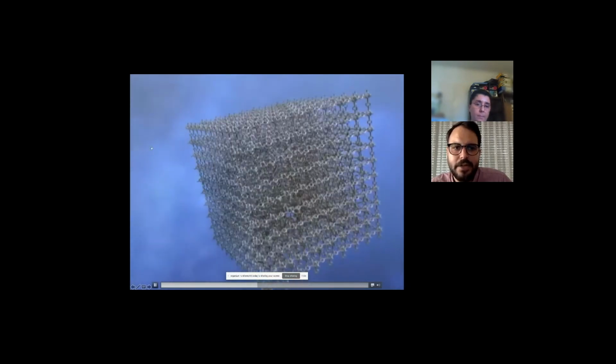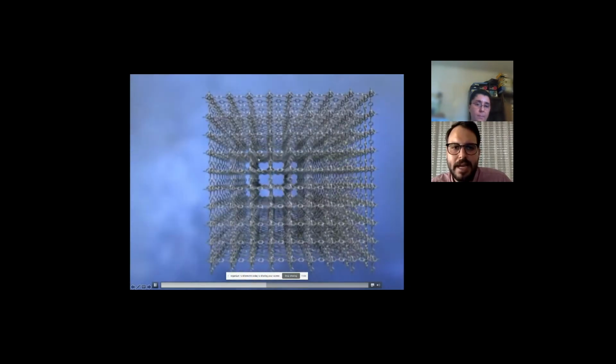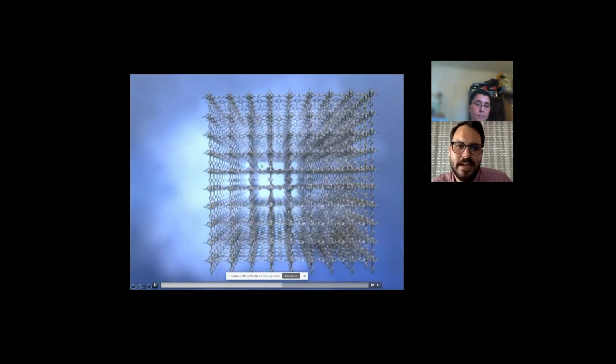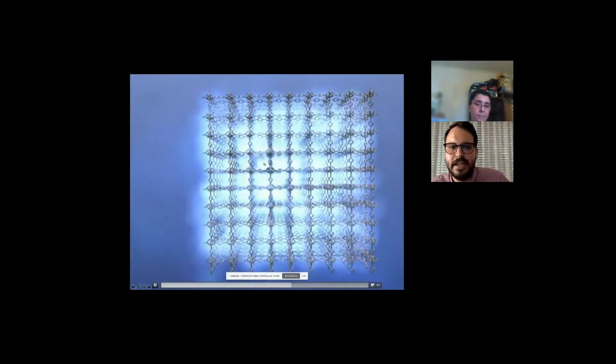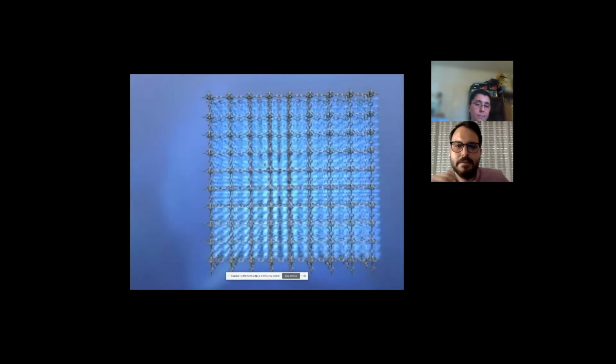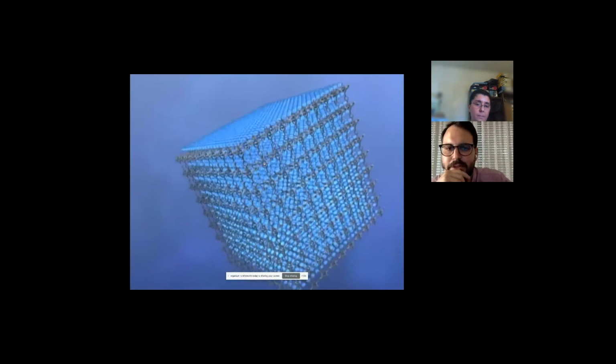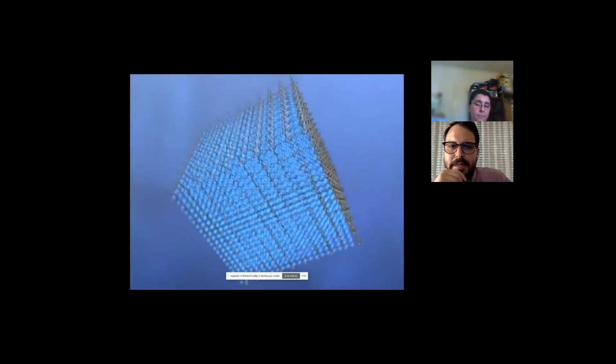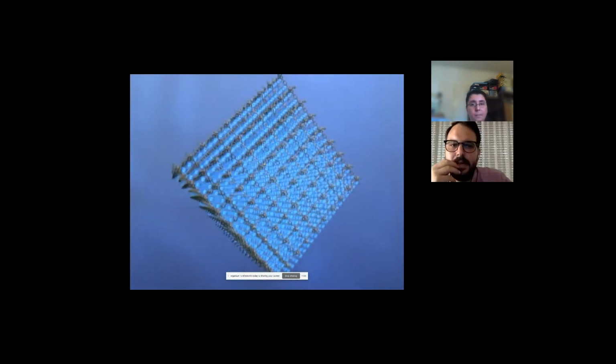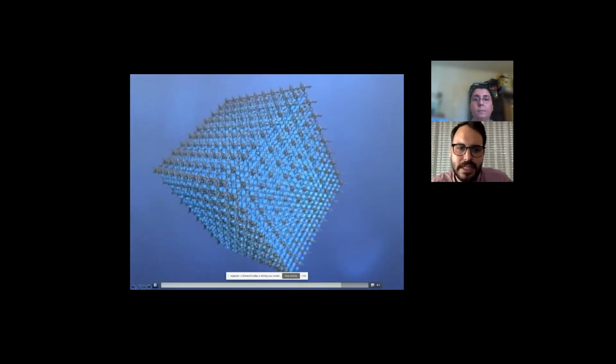And gas is starting to accumulate around it. Because we're able to tailor the interior, we can attract the gas molecules inside of the pores so that they stay closer together than if the MOF was not there. If you remember, gas molecules like to bounce around and they don't like to be compressed without high pressure. But in the case of MOFs, because of the attractive forces, we can pack gas molecules closer together. And so there you see these blue little species are the gas molecules stuck inside. So that's how these MOFs really function.